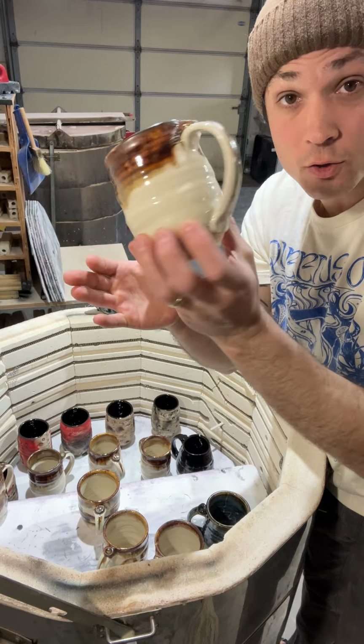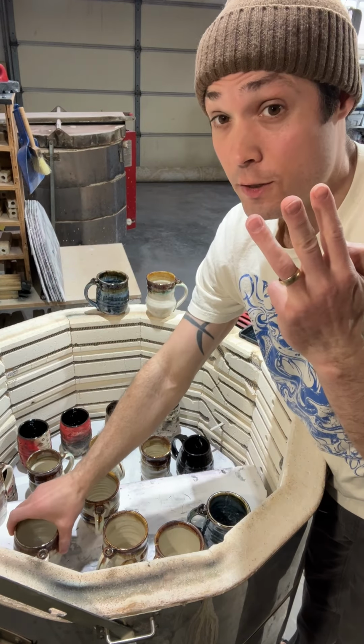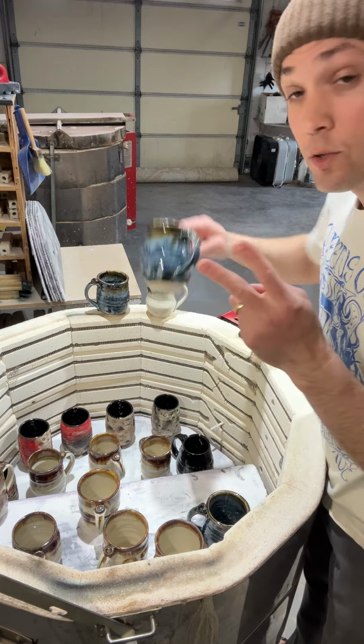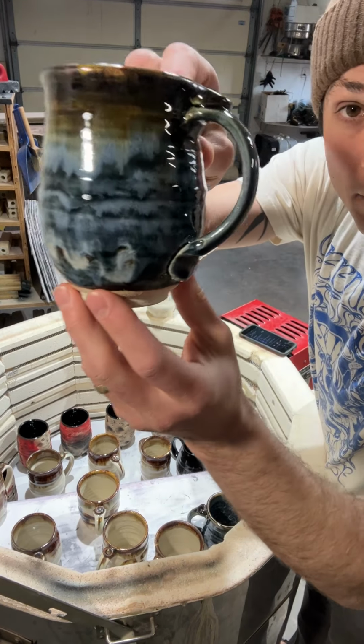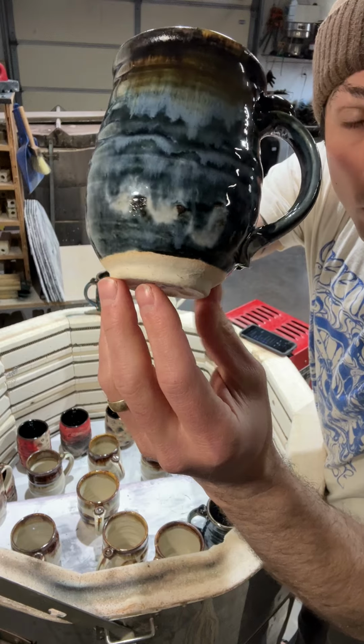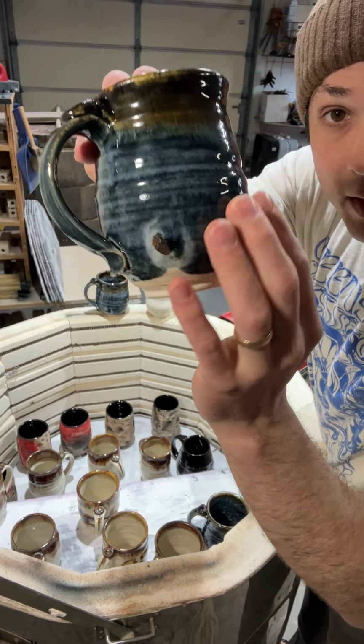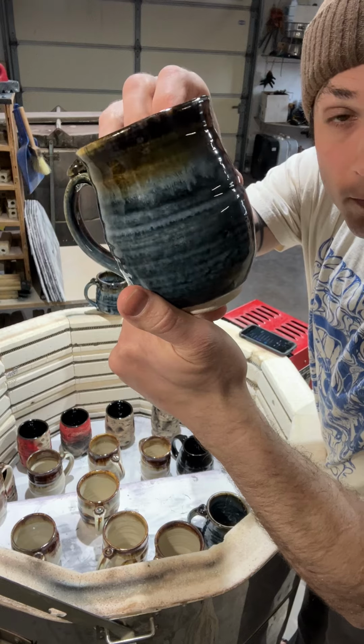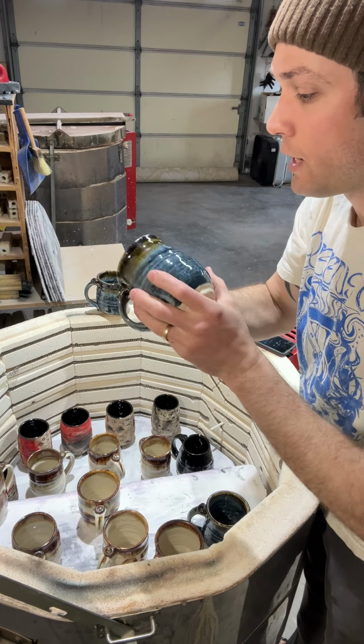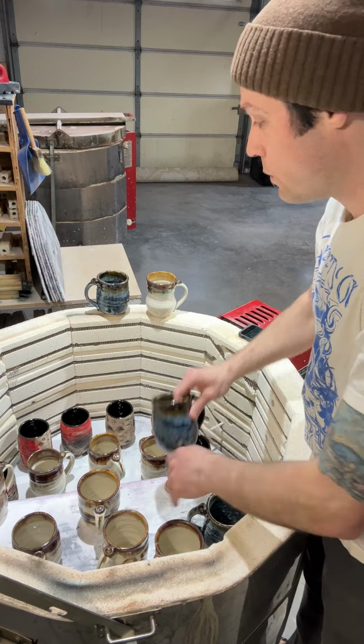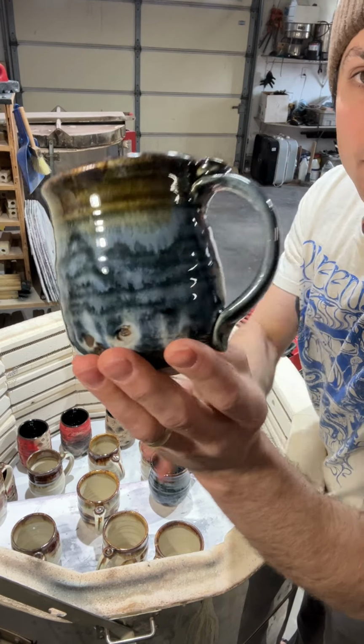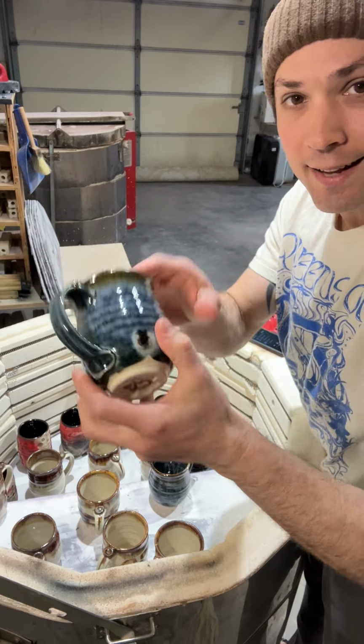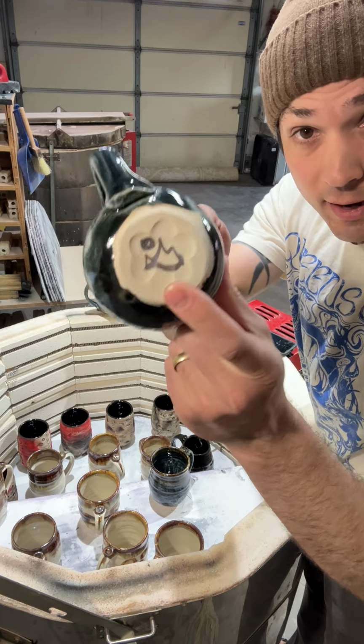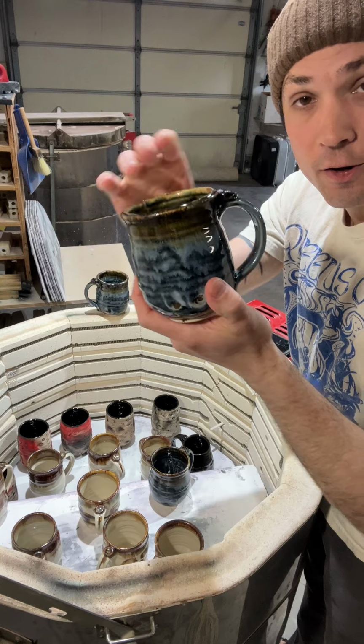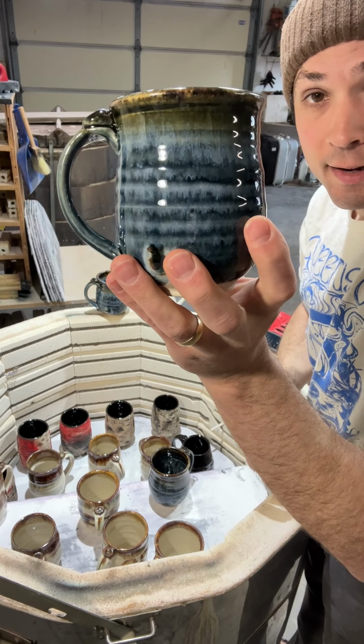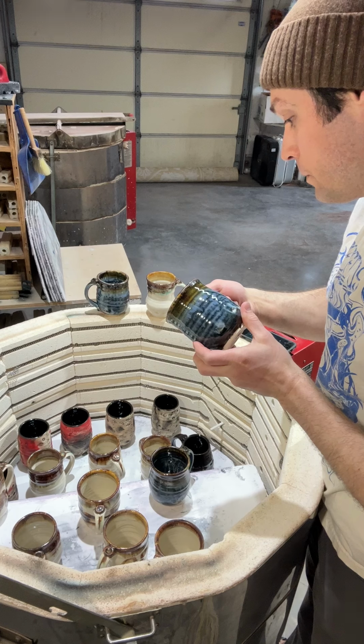And then, after it's dry, I put it back in the kiln and fire it a third time. These pots have all been fired twice. This one was fired 3 times. And that black glaze sticks to the surface enough where it melts and creates this dark blue. Sometimes it's a light blue, but it makes it so there's no bubbling of any kind with the additional firing, and it's this beautiful fluxy surface. So there's 3 of those in the kiln. That last time I forgot to sign them, so I signed them with iron oxide and then dipped them in the third coating of glaze for a third firing, and they turned out beautifully.